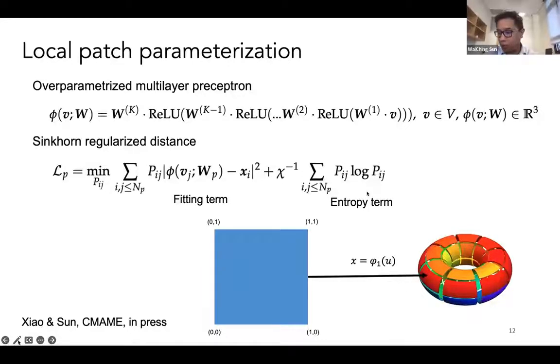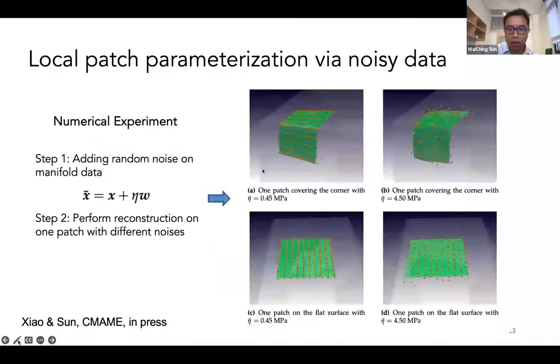In the classical way to create a yield surface, we will use the mean square error. Here we use the Sinkhorn regularized distance that comes from optimal transport theory. There's an entropy term there, and we will see why this entropy term is useful. We try to fit the data, but we also want to allow some level of entropy, and this entropy term could help us to overcome the noise.